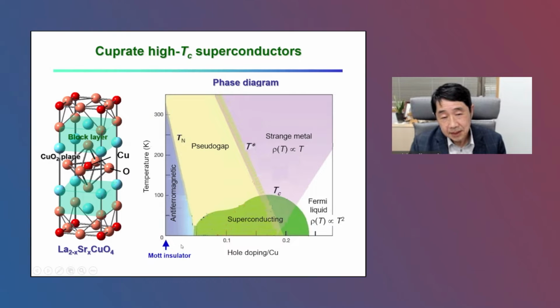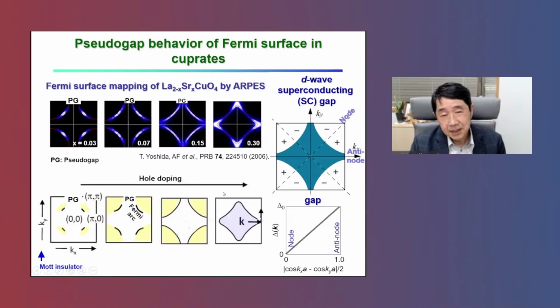In addition to the Mott insulating state and superconducting phase, there is a so-called pseudogap phase in which the density of states at the Fermi level is partially depleted when you go from overdoped to underdoped, and the pseudogap opens in the antinodal direction, leaving disconnected Fermi surface, so-called Fermi arcs, and with further underdoping, it finally vanishes.